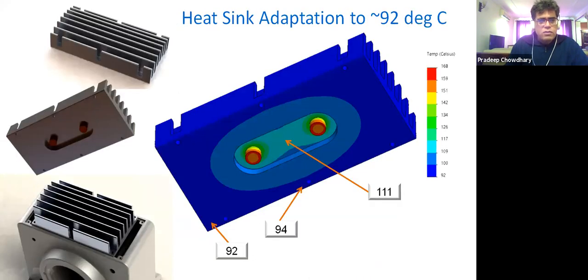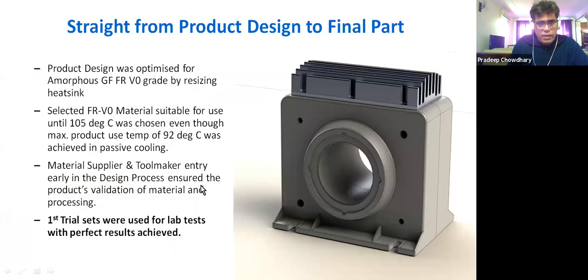So then the challenge was to redesign the heat sink, and we could not get the lower thermal profile because the heat sink was already optimized. So we used the housing to reduce the rounding on the sides and to create extra space for the heat sink, if you can see my mouse. So we managed to get about 20% more area on the housing opening for the heat extraction. So we were able to resize the heat sink doing that and drop the temperature down to 92 degrees, which was extremely comfortable for the new material.